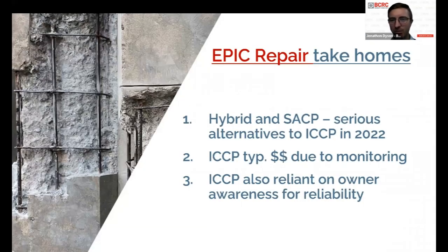So just some take homes from Epic Repair, our process for Epic Repair. In a nutshell, in summary of what I've been saying, hybrid CP and sacrificial anode CP systems are available in the market these days, and they can be serious alternatives to impressed current cathodic protection to provide proper cathodic protection for a given service life extension. Now, I'm not suggesting that there isn't a place for impressed current systems. Impressed current systems are oftentimes still the best idea. However, they do have some things that need to be considered. They can be quite more costly because of the monitoring, not necessarily more costly in the installation phase, but in terms of whole of life costs, once you factor in the monitoring that is required with impressed current systems over the life to make sure they're still working, then those costs can add up.